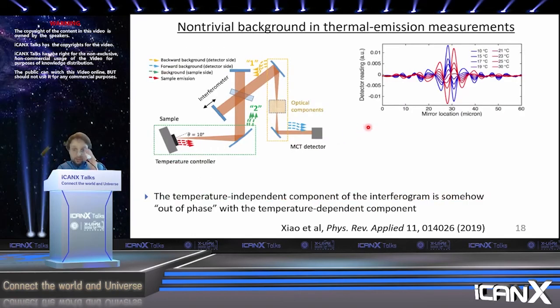So here is how we did some of this analysis. We measured the detector reading, what the detector is seeing as a function of the mirror position in the interferometer. This is actually how a Fourier transform spectrometer acquires spectra. You measure this interferogram, what the detector is reading versus the mirror location, and then you use a mathematical tool, in this case just a fast Fourier transform, to invert this data and figure out the spectrum of the light that's coming into the FTIR.